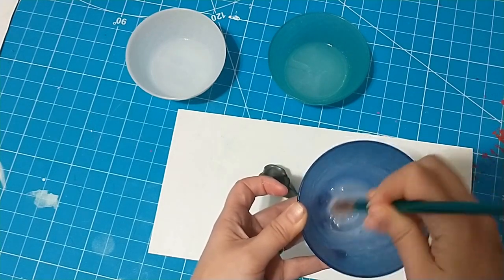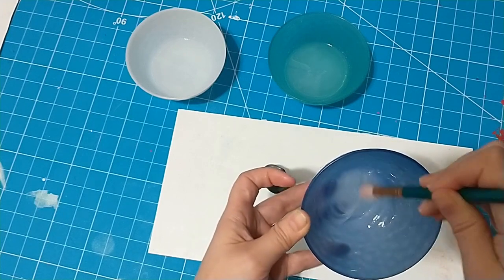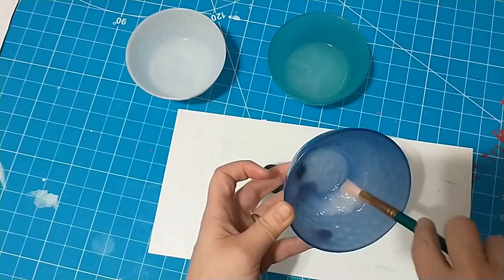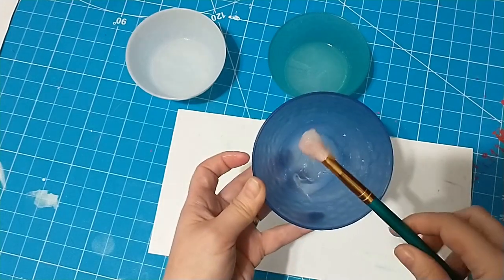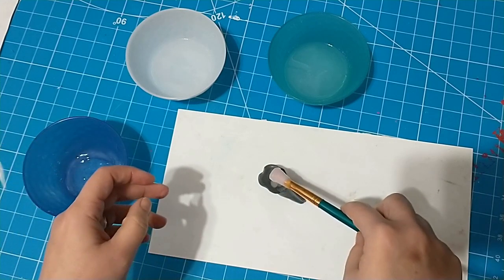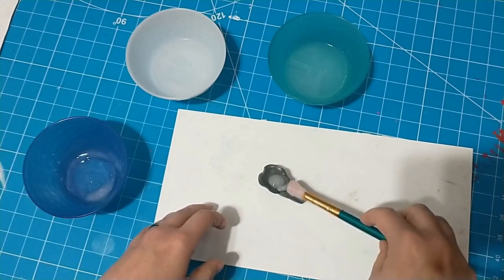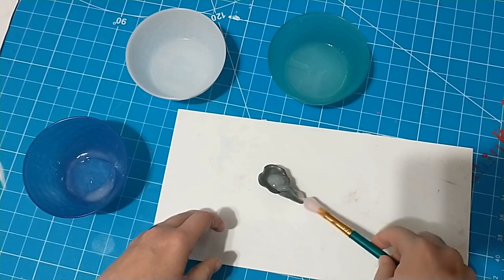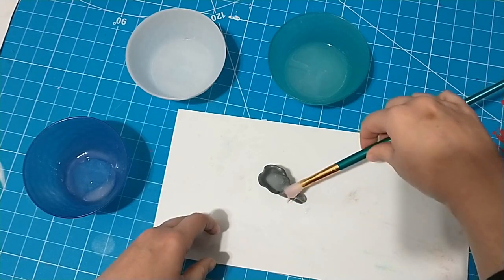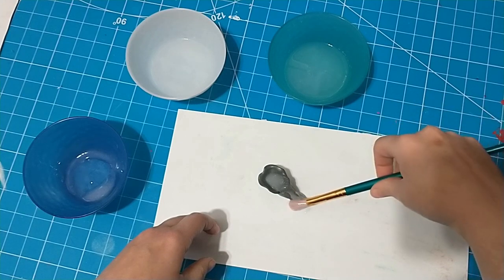You mix it up in the bucket before you pull it out, too, because the part that makes it cure, which does actually contain platinum, that's why it's called Platinum Cure. It's not like, oh, it's platinum best quality. I mean, it is the best quality. It's called Platinum Cure because it literally is made with platinum. That's the catalyst that makes it cure. Anyways, the part with the platinum in it will separate out to the bottom of the bucket. So you gotta stir good.